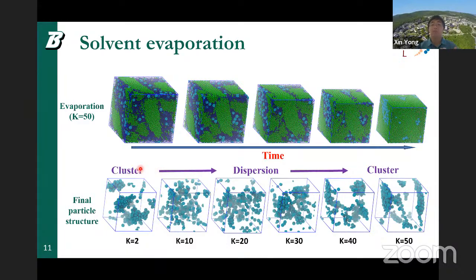Again, it's very non-monotonic. First of all, for a very soft chain, the particles will ultimately form isolated clusters, but these clusters are more isotropic. So we do not see any preference in terms of the elongation. And then due to the suppressed diffusion, the particles become more well dispersed in the matrix in the final structure at this intermediate rigidity. And then as we further increase rigidity, the particles start to aggregate again.